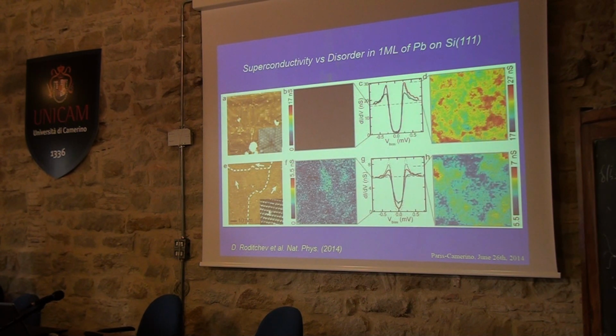We believe that it is not the lead which is superconducting, but the interface. The superconducting wave function in the vertical direction is strongly confined in this interface, and this is why every atomic step is a Josephson junction. So it is sort of a resonance state. We don't know how many mini-bands are participating. For the moment, it is not clear. We're trying to get a deeper insight about this, and it is basically the experiments we are running right now.